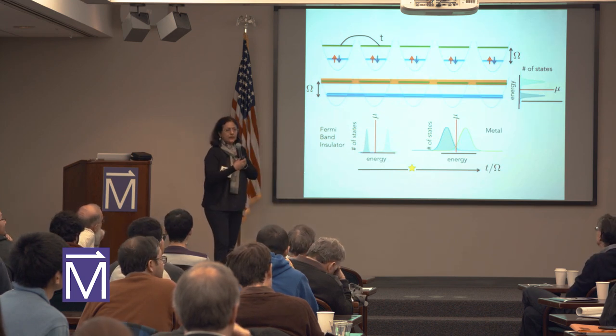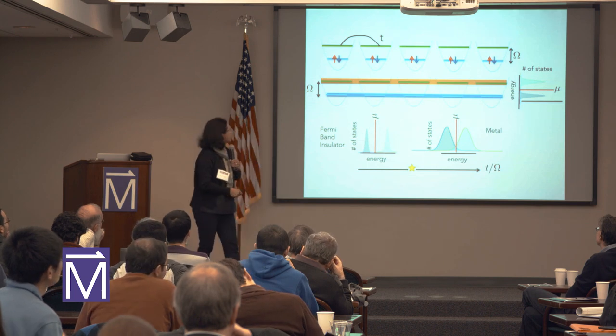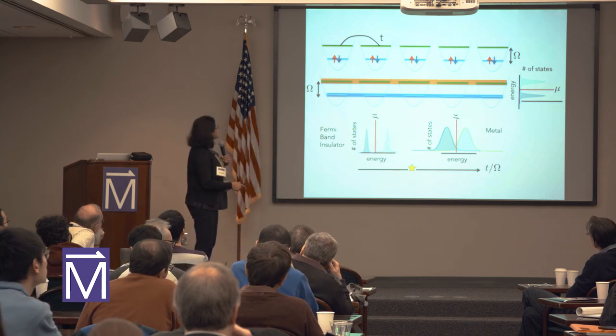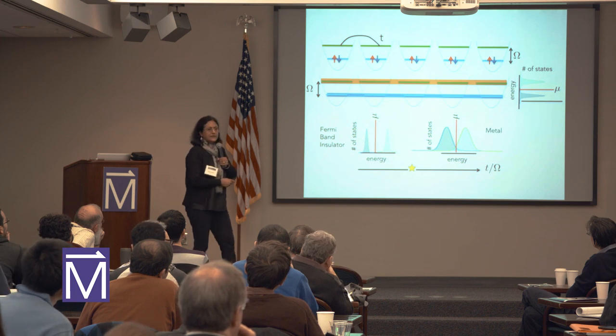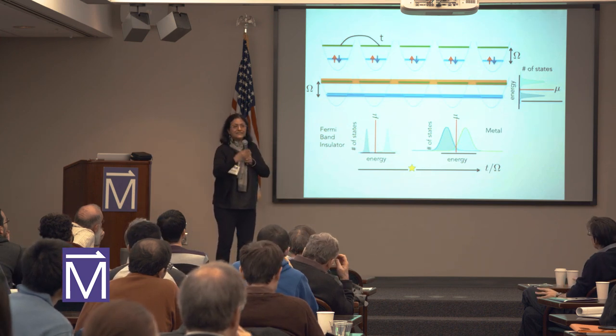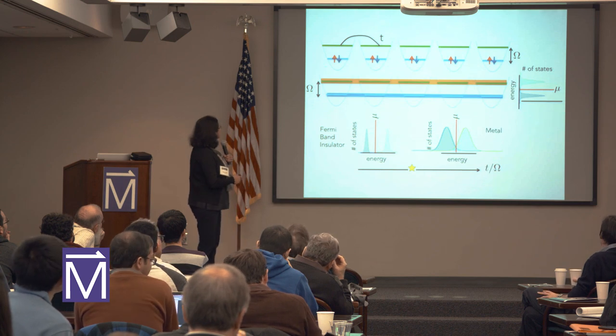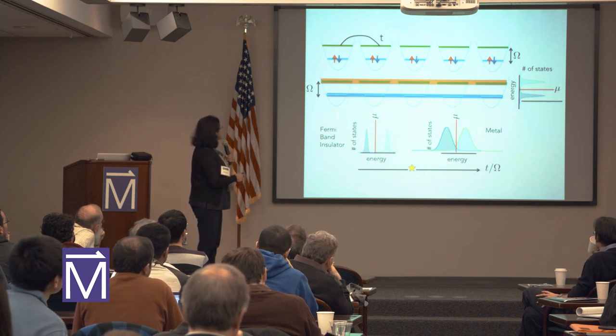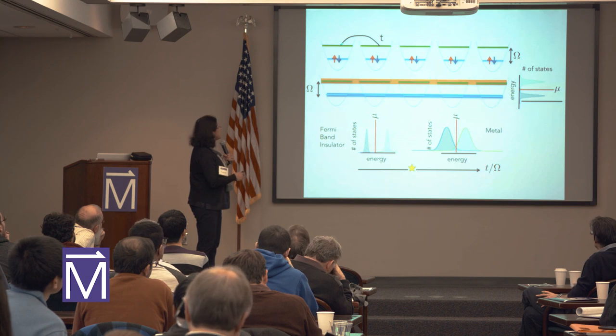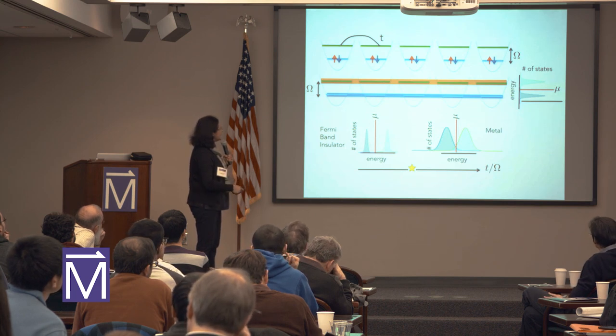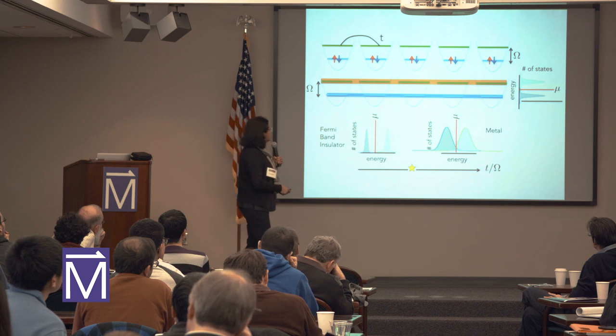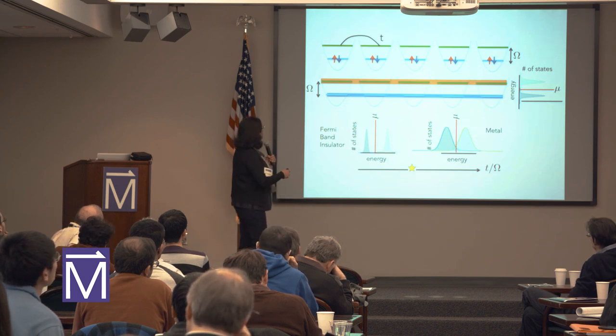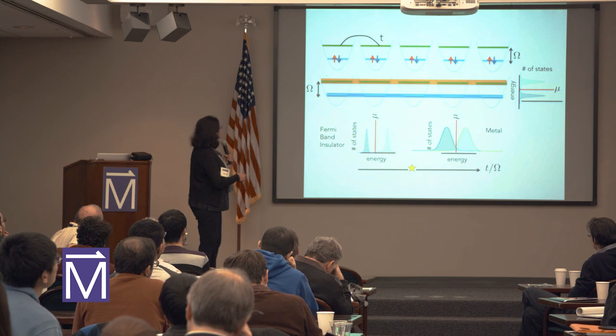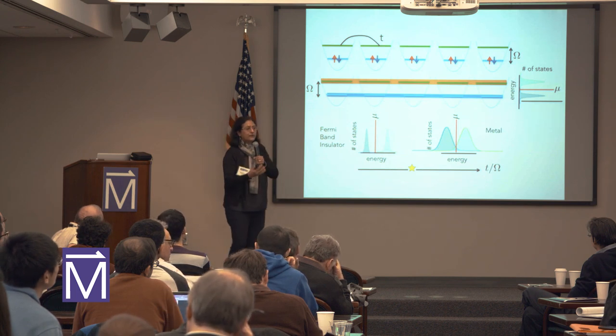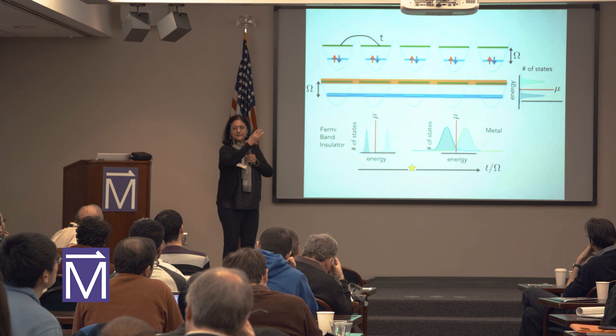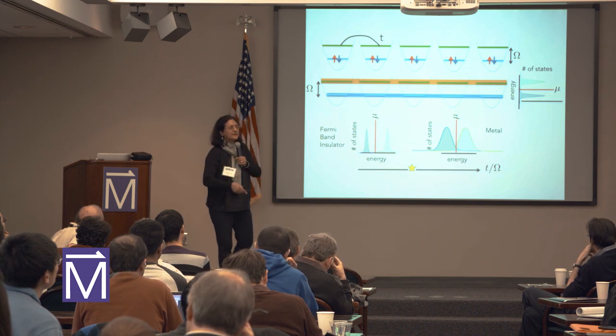So a way to realize that scenario is the following. I take different sites here. Each site has two levels. Because I want a band insulator, I need at least two levels per site. And this level is fully occupied. So then when you include tunneling, you essentially get two bands. In the absence of any attraction, there is a band closing at a critical value of the tunneling relative to the band gap in the single site. This is a particular realization of a band insulator.